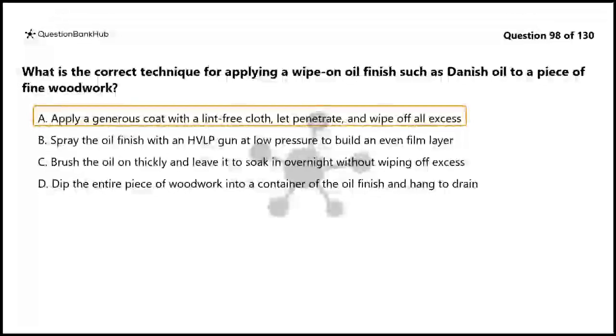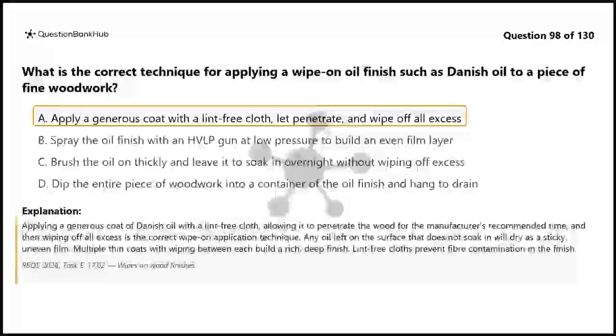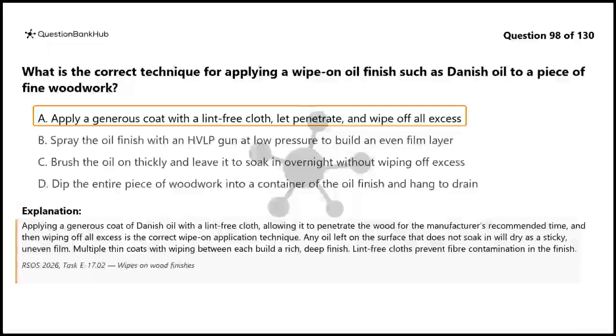The correct answer is A. Applying a generous coat of Danish oil with a lint-free cloth, allowing it to penetrate the wood for the manufacturer's recommended time, and then wiping off all excess is the correct wipe-on application technique. Any oil left on the surface that does not soak in will dry as a sticky, uneven film. Multiple thin coats with wiping between each build a rich, deep finish. Lint-free cloths prevent fiber contamination in the finish.